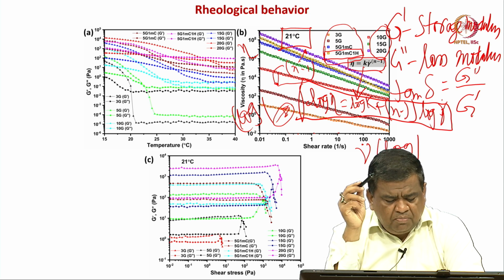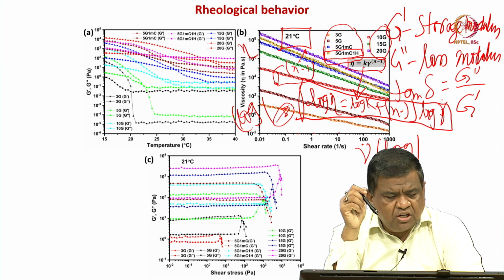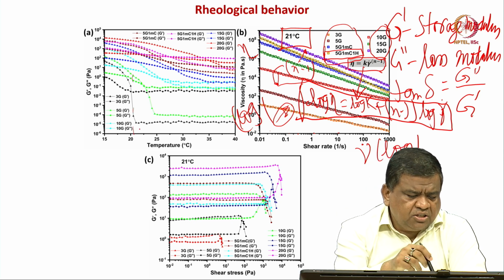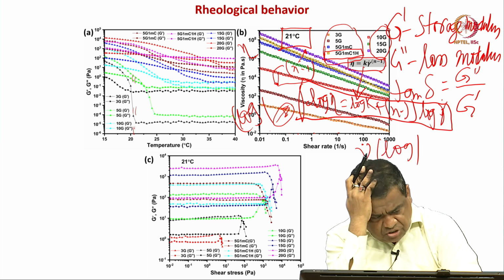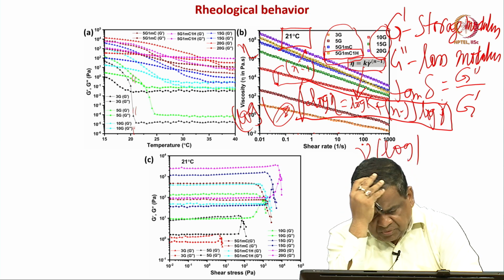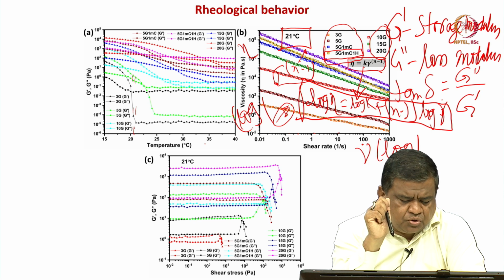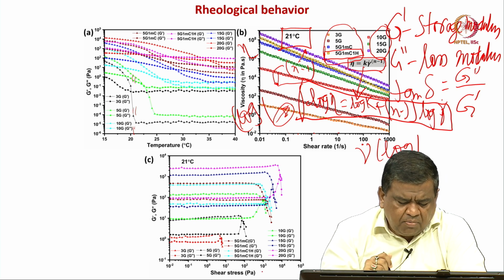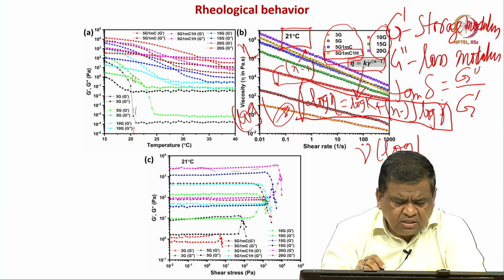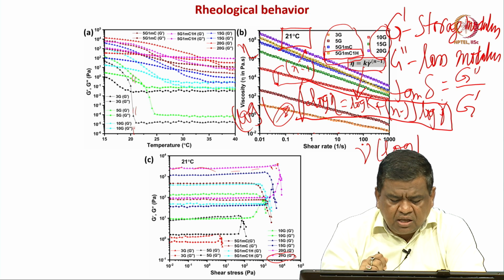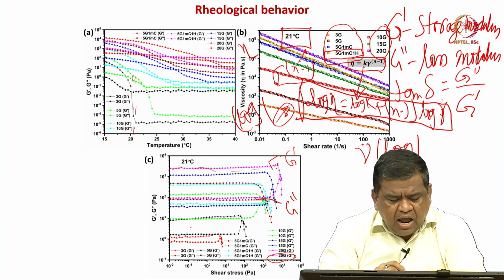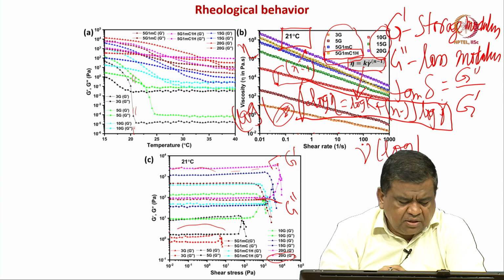Now, on the left hand side, G prime and G double prime as a function of temperature, and you can see why 21 degree Celsius in the temperature sweep. You can see how G prime and G double prime go through a transition. This is a temperature sweep, and in the bottom, G prime and G double prime as a function of shear stress. And if you see at 21 degree Celsius, up to large shear stress in the 20% GelMA, this is the G double prime, and these are the 20% GelMA G prime, and there is also the 3% GelMA.